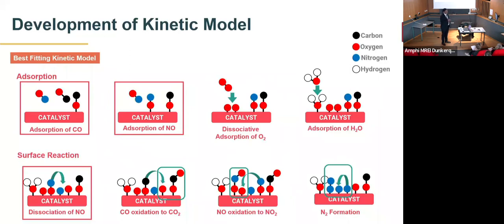The third thing is, even if there is a change in the material composition, like the species change over time, maybe you decrease your activity, but at some point you stabilize your activity. Let's say you decrease the activity by 15%, but you stay at this new level for a long time. It is sometimes possible, and we saw in our case as well, when we did cycles of light-off curves, at one point the yield was almost stable. So there are various possibilities.